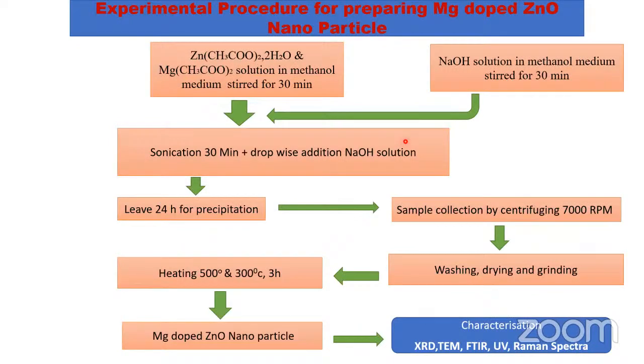Now, as for synthesis, we prepare Mg doped ZnO nanoparticles in our lab. We take acetate salt of zinc and acetate salt of magnesium, and we make a solution in methanol medium. After that, in another beaker, we make a solution of NaOH. After that, under sonication, we add the NaOH solution dropwise to the zinc and magnesium solution. And we sonicate it for 30 minutes. After that, we leave it for precipitation for 1 day.